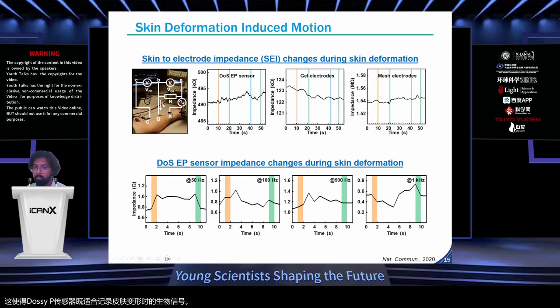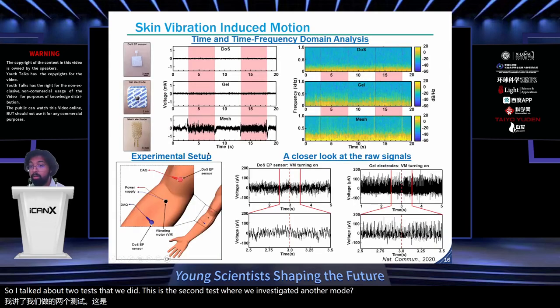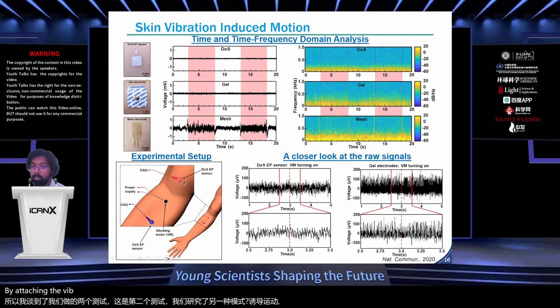So we talked about the first test; in the second test, we investigated another mode of induced motion by attaching a vibrating motor nearby the sensors to simulate shaking of the arm. Here we recorded resting muscle activity while the vibrating motor was turned on and off. The on portion is represented by these pink bars. In these time domain signals, DOS-EP sensors and gel electrodes don't show much of a difference, whereas the mesh electrodes are substantially affected.